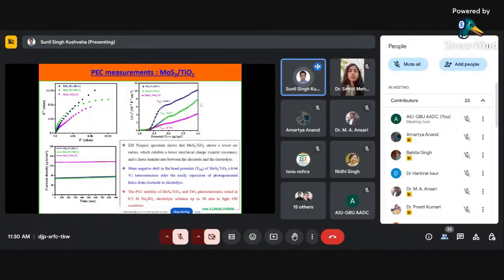That is showing what the resistance is inside the electrochemical cell. Basically, it is measuring the impedance of the electrolyte plus electrode interfaces. Most of it depends on the formation of the arc, and whenever the arc of this EIS Nyquist plot is lower, it shows low interfacial charge transfer resistance. So it will help produce a faster transfer rate between the electrode and electrolyte if you have lower interfacial charge transfer resistance. If we compare, the MoS2 coated TiO2 has the lower one, so that is the reason we are getting very high current density compared to the TiO2 and Ti.